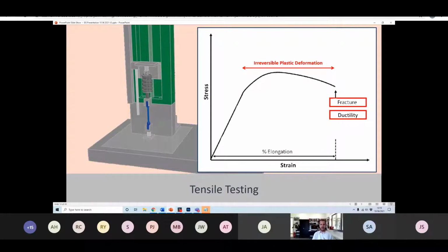So actually, let's start this time by first defining what ductility is. And it's really a material's ability to sustain plastic deformation before failure. So it's about the degree of tolerable strain. Okay, and that definition actually is, well, I would say completely uncontentious. I think everyone would agree that's what it is, and that's apparent on the stress strain curve that we're showing here. But there's something rather important about ductility which is not always very apparent, and it's something that is less well understood, which is that ductility, or ductility values, which are nominal strain values at fracture, well, a ductility value is not a fundamental material property, like, for example, the yield stress is. Okay, it's really important, actually.